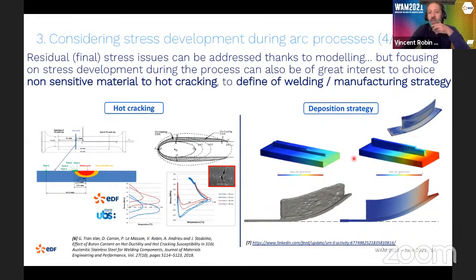And the other thing is that if you use transient analysis like we do for computational welding mechanics, you can optimize the strategy for weld deposition, reducing distortion, or sometimes also check to prevent hot points for residual stresses.